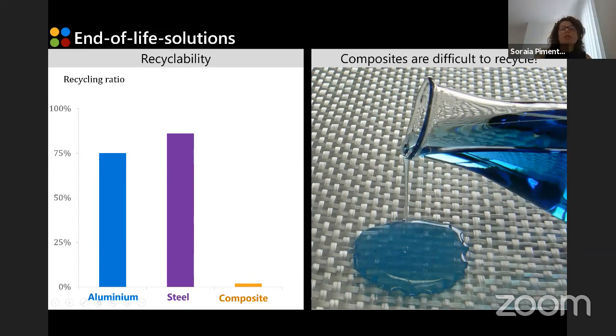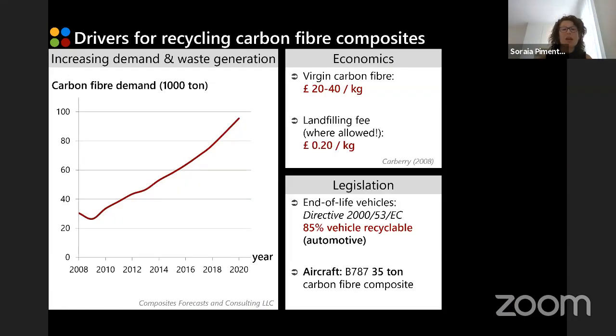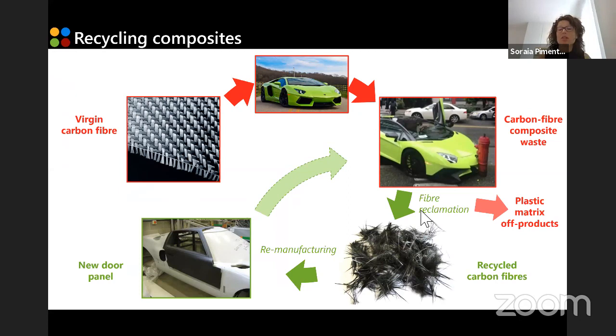Of course, with the increasing use of carbon fiber composites, together with the economics of the process and also some incentives from legislation, it becomes more and more important to recycle. And as Steve already mentioned, basically the process that we use is that we remove the matrix from the composite, recover the fibers, reimpregnate the fibers with a new matrix, and create a new component in a loop that can continue.